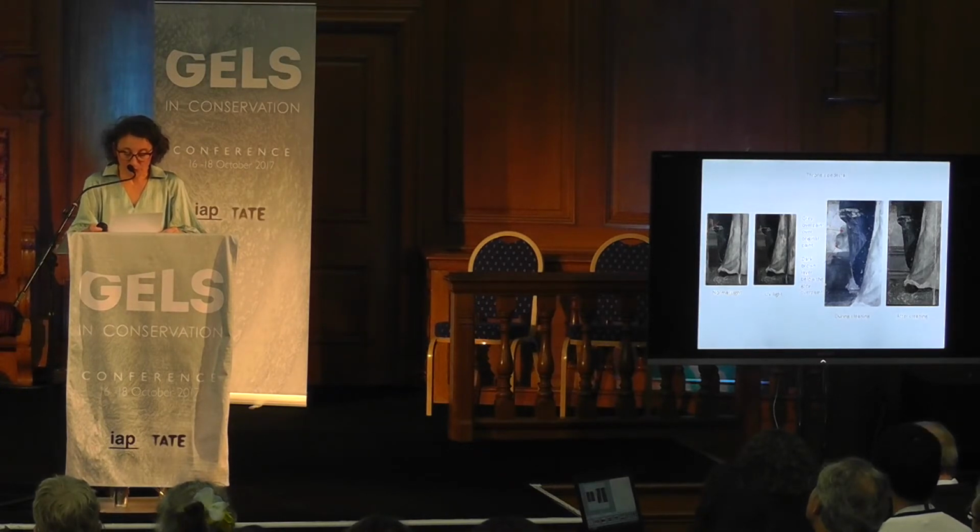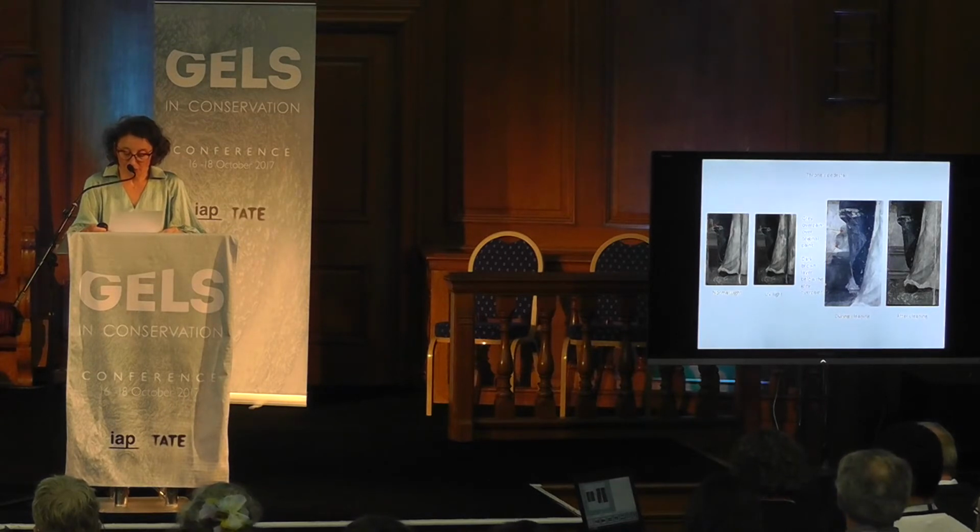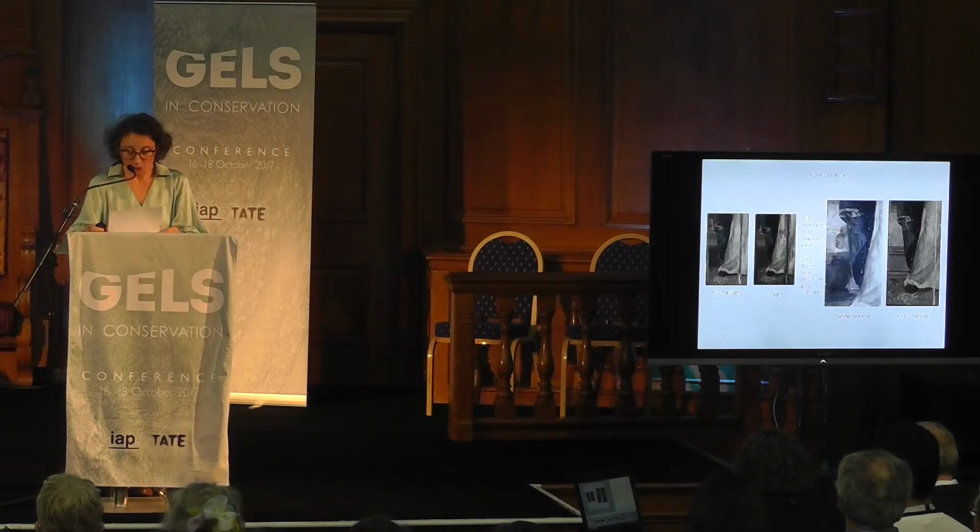As the removal progressed closer to the uneven varnish of the original surface, a weaker xanthan gum emulsion with citric acid at a pH of 7 was used. The benzyl alcohol concentration varied according to the thickness of the overpaint and sensitivity of the original paint. Any remaining overpaint residues were removed mechanically in order to preserve the thin old layer of varnish.